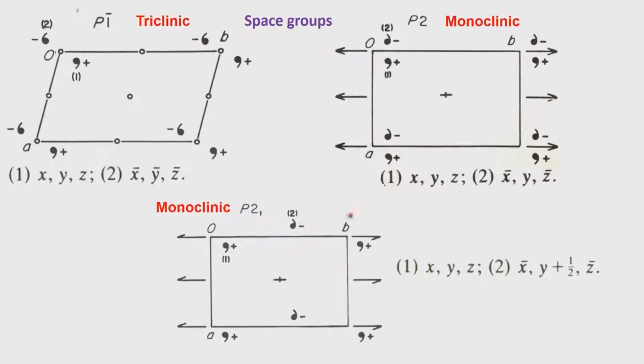So, in this particular case you have x, y, z, the rotation axis is y, and therefore the translation is along the y direction. So, x changes to minus x, y changes, z changes to minus z. So, you generate this by a two-fold symmetry operation plus a translation along the direction about which the axis operated, and so we get to this position. Now, this position on one translation will bring it down here, telling us that we do have a two-fold symmetry operation at half position, and these two now become the equivalent points in the unit cell corresponding to the coordinates x, y, z, x bar, half plus y, and z bar.